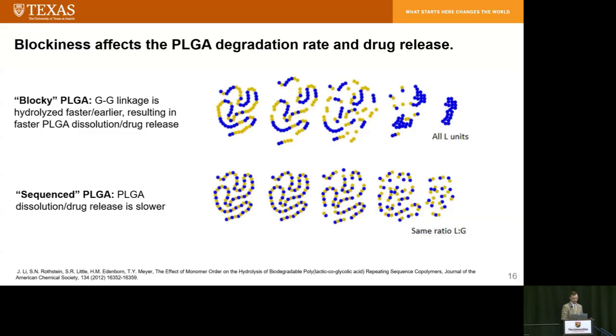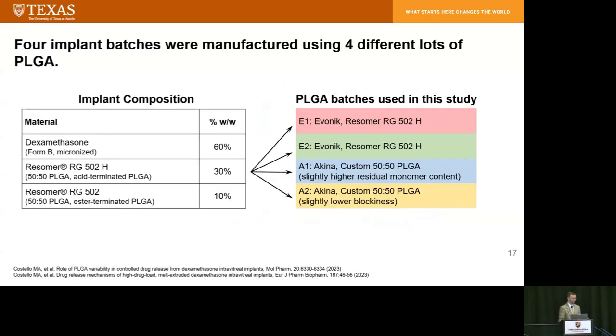In the context of generics, this is important because you could have two different PLGA batches that appear to have the same bulk composition, but they actually have different blockiness and thus different degradation and drug release behavior. Therefore, PLGAs from different suppliers could have the same bulk composition, and they could appear the same by standard analytical measurements, but they could actually have different performances due to different blockinesses. So we wanted to explore this in the context of Ozurdex.